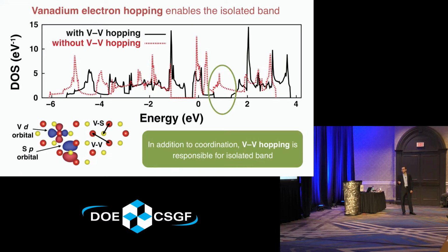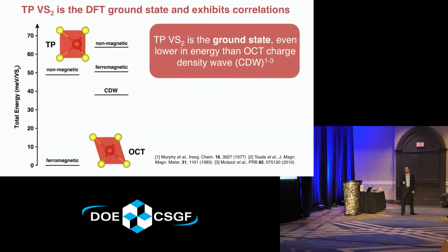So now that we've achieved that property, we wanted to see, okay, can we actually make this thing? So we wanted to consider the thermodynamics. So basically, we computed the energy of different structural, electronic, and magnetic states to see what's lowest in energy and by how much. If you first look on the right here, you'll see we have to consider our existing octahedral phase to see if it's higher or lower in energy. You can see we have a non-magnetic configuration. There's a magnetic instability that lowers the energy. Experimentally, it's known that there's this complicated structural distortion called a charge density wave in this system. We capture that it further lowers the energy.